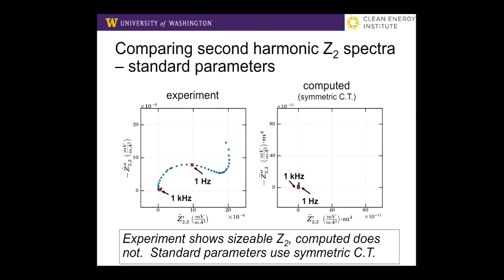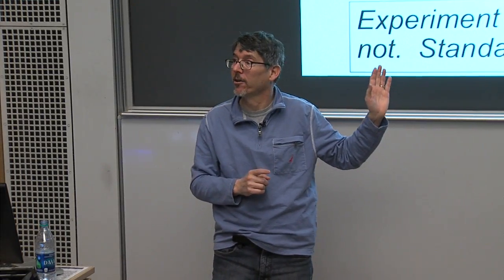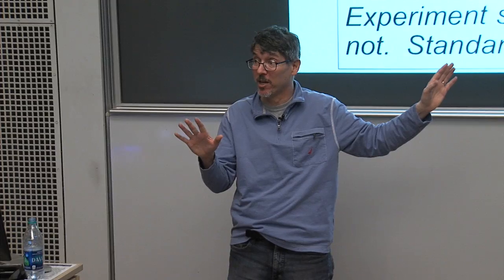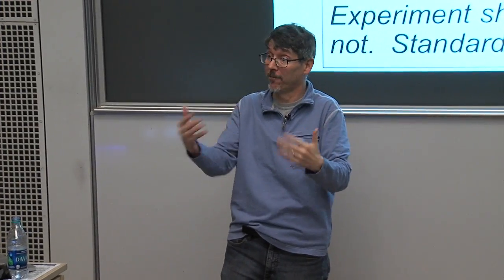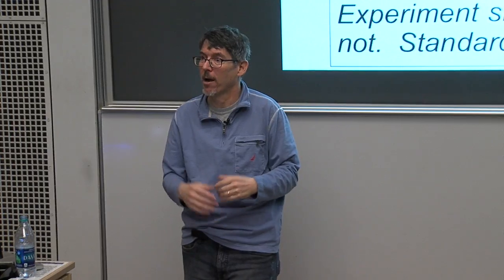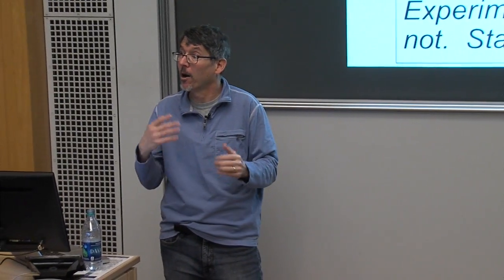And the reason is that the standard model and the methods that they've been using can't see the asymmetry of the reaction. When we just assume symmetry in charge transfer on both electrodes, effectively we've squashed the second harmonic with the standard parameters when we use them from the literature. And so there's a lot we can do. In fact, if I just change one parameter, I can start moving towards a best fit. Now, we're not going to do best fits because this is really new data, but we will eventually get to doing best fits of parameters and seeing how much information we can glean about the physics inside the battery.